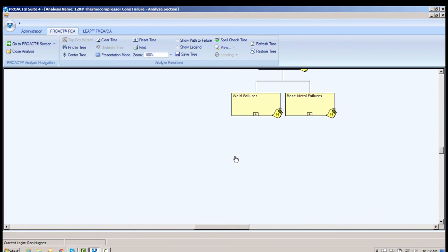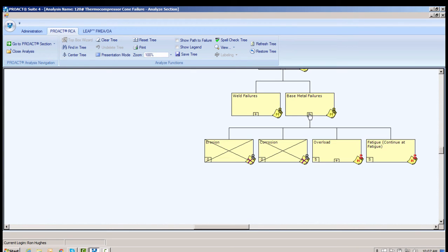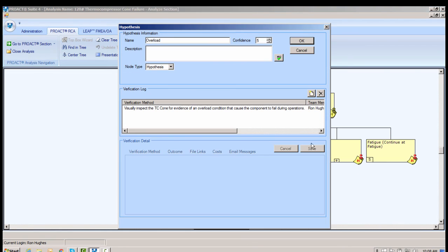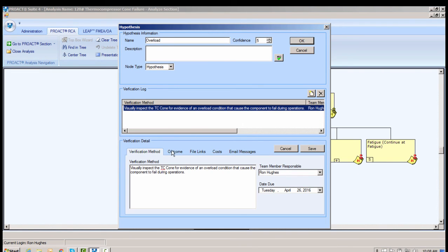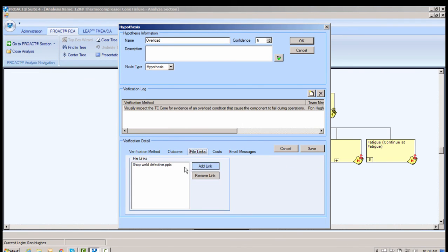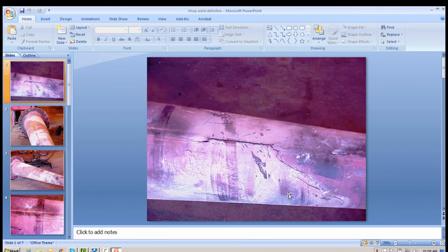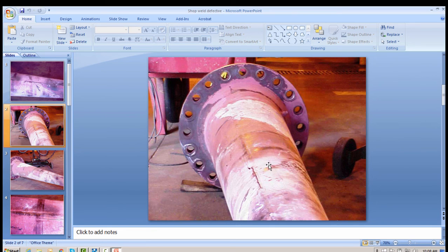Okay, this is the base metal failures. Let's look at these. How can the base metal fail? Erosion, corrosion, fatigue, and overload. Again, notice fatigue. Fatigue occurs over at the welding where we've manufactured the cone and has already been covered. But it's definitely been overloaded. So just by visual examination, we verify overload. And we can see from my pictures here, it's obvious that the weld is cracked and definitely overloaded.